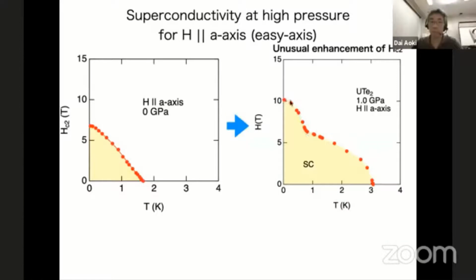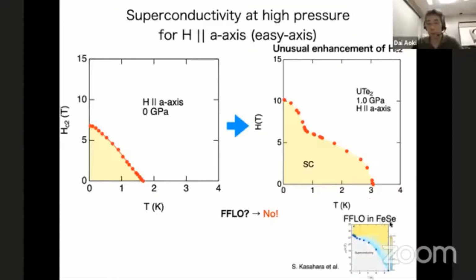From this curve, you may think about the possibility of FFLO, but it is not the case. For example, in iron selenide, the FFLO state was reported by Kasahara. You can see here that they claim this is an FFLO state, and this increase is very small in the case of FFLO. But here in uranium ditelluride, it's a very large increase. This cannot be explained by simple FFLO. And so we measured AC calorimetry to study the inside of the superconductivity in more detail.